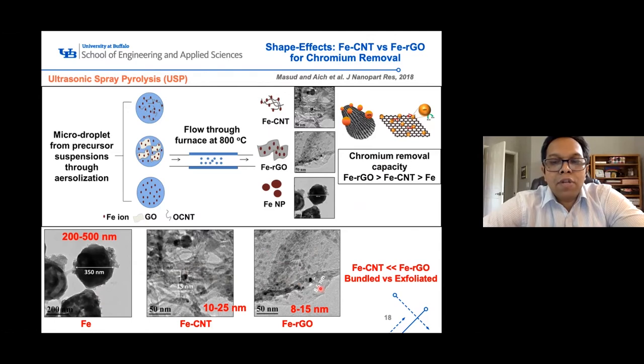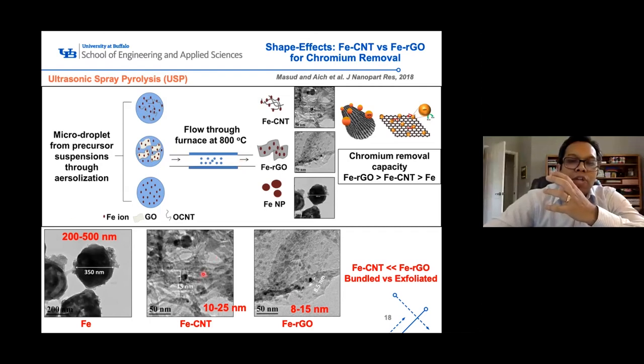But what happens in carbon nanotube versus graphene is that when this carbon nanotube and iron droplets go through the furnace, because these are a lot of carbon nanotubes, tube-like structures, string-like structures, and the water goes away, basically they collapse and they form a porous structure. And the irons are inside them. On the other hand, in case of graphene, these individual sheets go through this furnace at high temperature, they actually separate out from each other. They don't collapse onto each other.